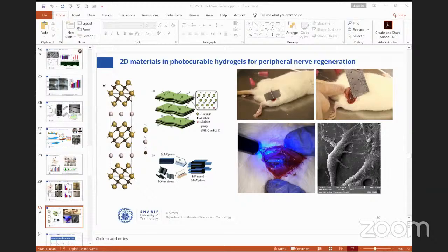treatment of the nerve system. The polymer which we use was light active, so using a UV light, we could cure the scaffold. As you see in the right-hand figure, the peripheral nerve from the leg of a mouse was cut for 1 centimeter. We inserted the scaffold and the gel inside by irradiating a UV light. We cured the materials, and you see in the SEM picture the surface after a while. The cells stick to the surface, and the nerve was regenerated. This is also one of the newest results of our work, in which we use MXene inside a curable hydrogel for the nerve system.